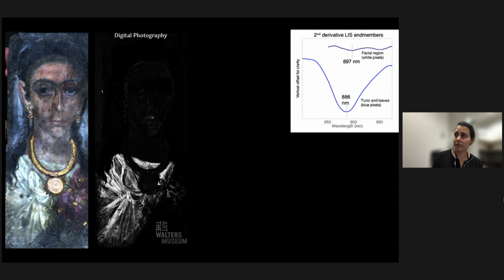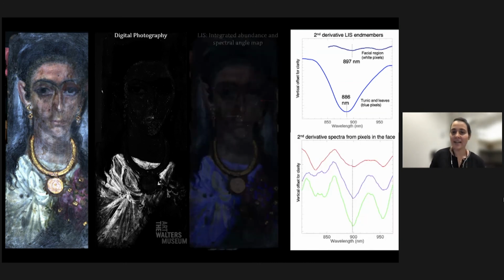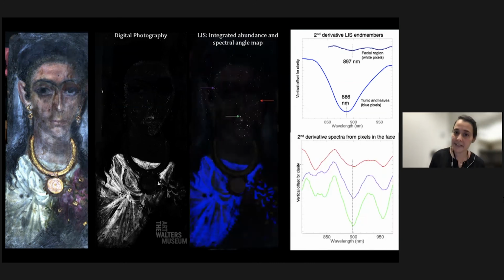Now, what we struggled with a little bit was with the face. So I took the data cube and I calculated a second derivative, which takes the luminescence peak and makes it an inverted signature because I really want to access those really subtle signatures. And then I data mined the cube again, and I found two signatures, one that corresponds to most of the tunic and one that corresponds to the face. And if I select out some pixels that we can also see in the digital photograph, we see that inverted peak around 900 nanometers that is corresponding to Egyptian blue.